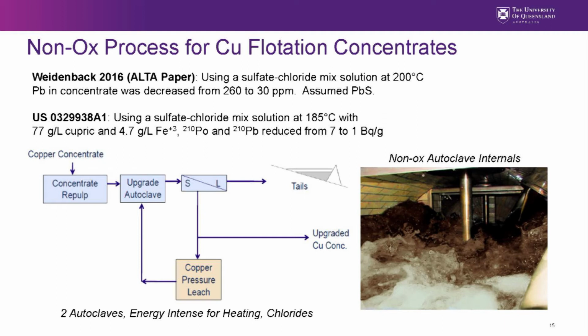So this is a simplified flow sheet of the process. You take your copper concentrate, you send it to this upgrade autoclave at, say, 200 degrees, and you introduce a very concentrated copper sulfate solution into the autoclave. The metathesis reaction takes place. You separate the solids from the liquids, and you end up with an upgraded copper concentrate. There's a split there. Some of that is recycled to a second autoclave process in this case, because it's expensive to purchase all this copper sulfate. So you generate the copper sulfate from the copper concentrate itself. So it's two autoclave processes, and they're integrated.